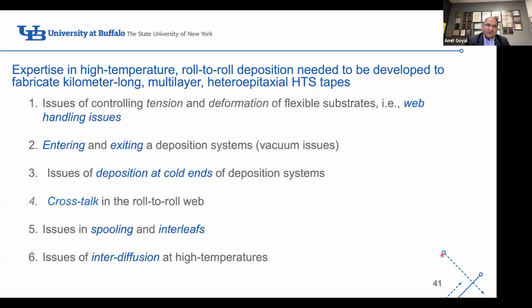So we had to address all of these issues by research, looking at what happens when you're handling a web at high temperature, tension and deformation of flexible substrates. How do you enter and exit a deposition system? How do you avoid deposition at cold ends, where you don't get epitaxy in the right orientation? How do you prevent crosstalk in a roll-to-roll web? How do you spool the tape and put interleaves so that there are no reactions? How do you prevent interdiffusion between all these multilayers? All of this had to be addressed before roll-to-roll deposition and kilometer-long wires could be made.